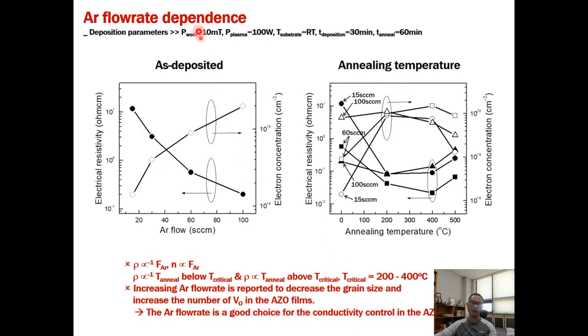Third, I will show argon flow rate dependence. In the left figure, electrical resistivity decreases with argon flow rate. Electron concentration is vice versa. In the right figure, electrical resistivity decreases with annealing temperature until 400 degrees centigrade. Above 400 degrees centigrade, it has a tendency to increase. Electron concentration is vice versa.